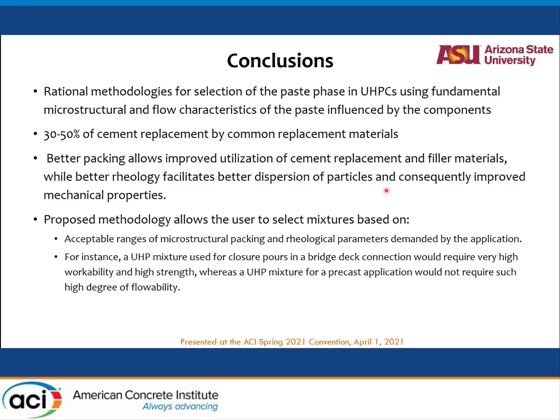What this method does is, using simple rheological tests in the lab and simple particle packing tests, which use only the particle size distribution of the components of the mix that you're using, you are able to develop both of those indices and then combine them, and then do some initial tests to see what you would want, tweak the model or the multipliers based on what you want, and come up with a valid combination of the binder.